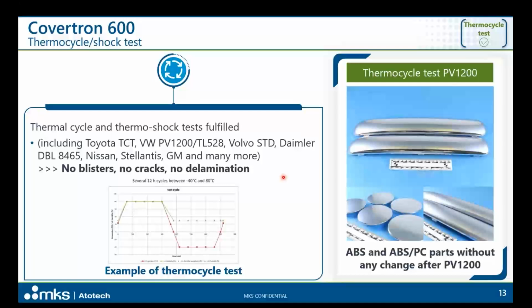Just as an example, we can mention the Toyota thermocycling test, the very famous Volkswagen PV1200, the Volvo, the Daimler, and Nissan. We have fulfilled, and we are fulfilling all of them without any blister, crack, or delamination of the parts. Here on the screen, of course, you can see the results after the Volkswagen thermocycle test PV1200 for ABS and ABS-PC, and there is no change after this thermocycling test.